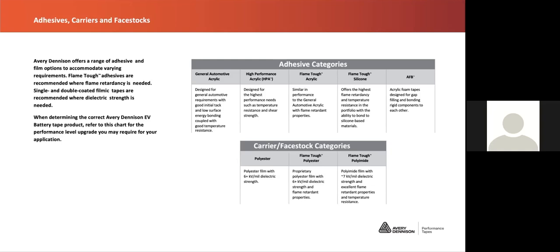These are acrylic foam tapes that are designed for gap filling and bonding rigid components to each other. Then the carrier and face stock categories, we have a traditional polyester that has about 6 kilovolts per mil of dielectric strength. We are introducing a new flame tough polyester that has similar dielectric properties, but also the added benefit of flame retardant properties. And then we're also introducing a flame tough polyimide, which has even better dielectric strength and even better flame retardant properties.